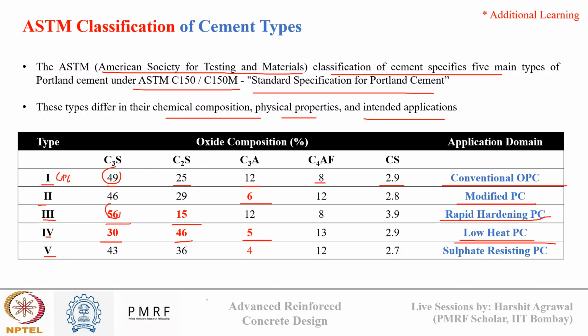Okay, and then we have type 5, which compared to type 1, if you see, C3S is comparable, and it has a very low C3A content. Okay, so this type of cement is known as sulfate resisting cement, because of its very small C3A content. Okay, so like this, just by varying the oxide and compound composition of a cement, ASTM has generated five conventional types of cement.